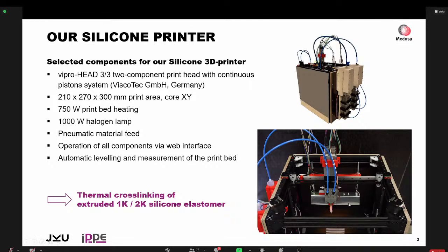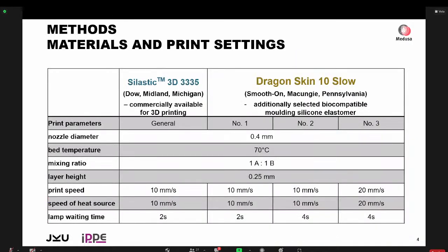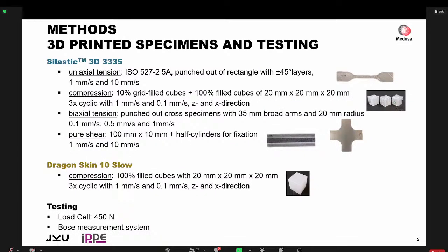After each layer, so conventional extrusion-based additive manufacturing, after each layer, we go over it with a halogen lamp, which produces a lot of heat. So we have thermal cross-linking of the silicone elastomers. There's actually only one silicone advertised for this purpose. This is the Silastic 3D 3335. And we also wanted to check out if we can print with other kinds of silicones. For example, we have here a biocompatible, usually molded silicone elastomer, the Dragon Skin 10, and we use the slowly cross-linking one. There are print parameters, but you can also see the details in our paper.